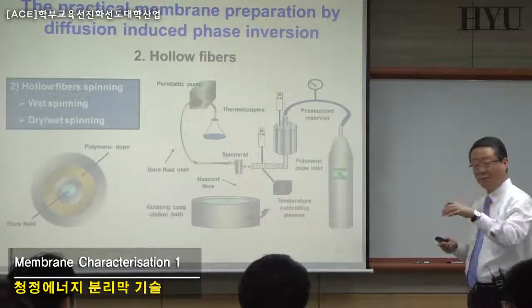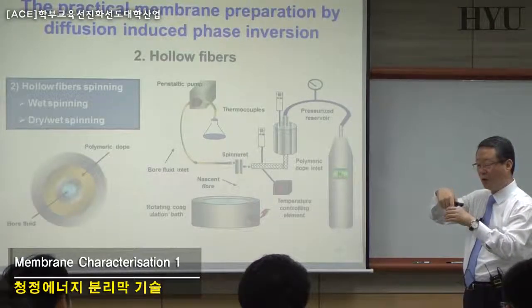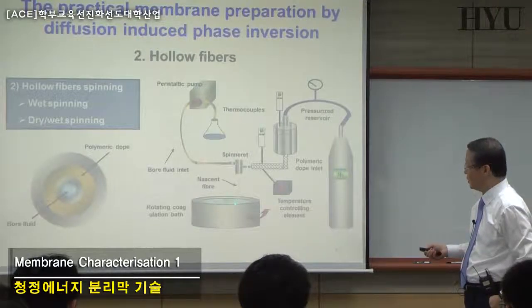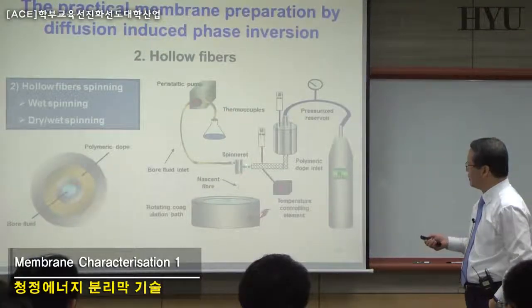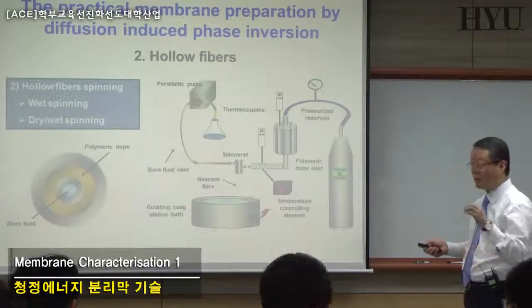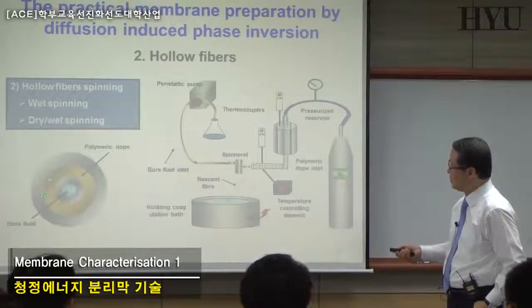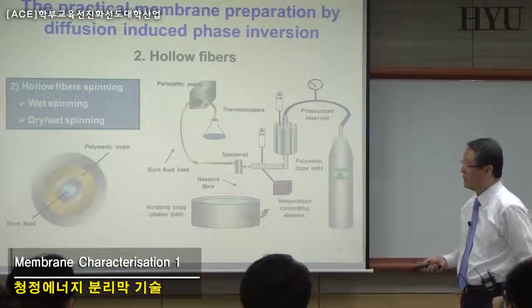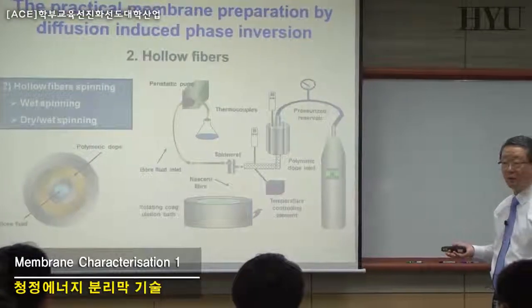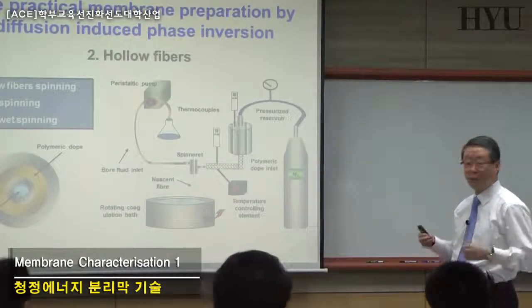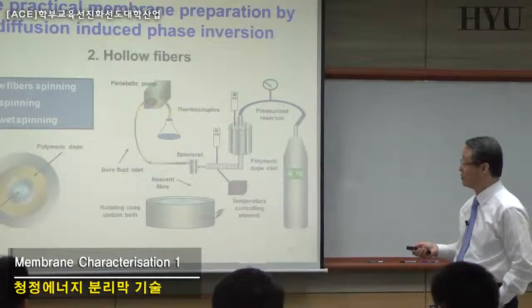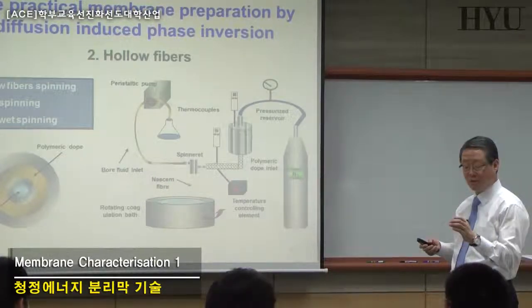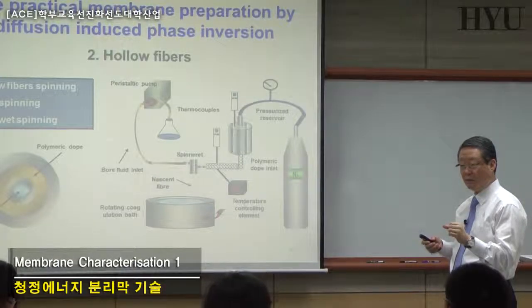And the polymer solution, along with the bore fluid, is coming down from the spinneret into the coagulation bath. I'm sorry, so into this small diameter of the spinneret. Usually the diameter from here to here is around several hundred micrometers for the gas separation membrane. If you're making the water separation membrane, then the diameter might be a little larger, up to about 1 millimeter or about 1,000 micrometers. If you want to make it smaller, then you intend to use this fiber at high pressure.